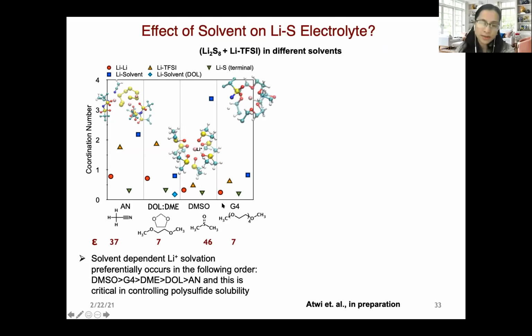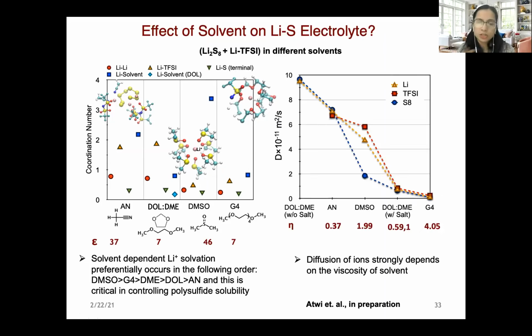And glymes were again an interesting solvents because of their structure and their ability to wrap around the cation. They can dissociate the cation from the anions. And we observed the effect of this change in solvation structure on the dynamical properties. And there we found another parameter which plays a crucial role. And this parameter is the viscosity of the solvent molecules. So we found that the diffusion of ionic species is fastest in acetonitrile because it has very low viscosity. And it's second highest in DMSO. And now you should be asking me a question that the viscosity of DOL DME is actually lower than that of DMSO. Then why is the diffusion faster?